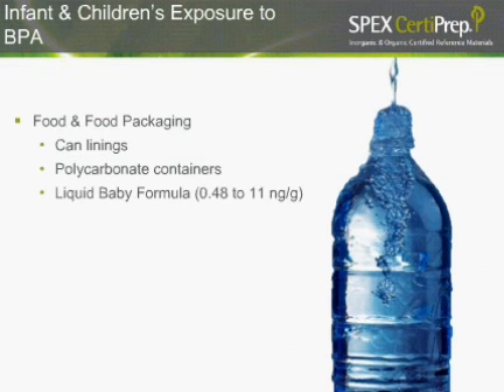The routes of exposure children have to bisphenol A primarily can be from food and food packaging. A lot of can linings that are used in cans with acidic foods, things like tomato sauce and soup and such, can have an epoxy lining that contains bisphenol A. There was also a lot of talk about bisphenol A and polycarbonate containers. So there were a lot of bans for polycarbonate baby bottles. And not too long ago, a liquid baby food formula study showed that there was 0.48 to 11 nanograms per gram of bisphenol A in the baby formula.